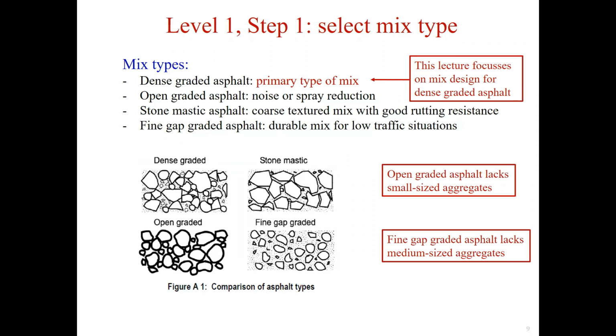The open graded asphalt is characterized by a large proportion of coarse aggregates and only small amounts of fine aggregate and filler. Due to large voids, its usage can lead to reduced noise and reduced surface water and spraying.